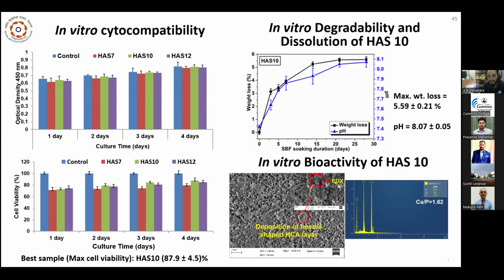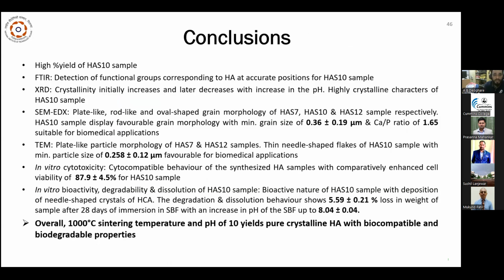Here it shows that a needle-shaped structure is observed with a calcium phosphate ratio of 1.62. From the analysis, it can be observed that at a sintering temperature of 1000 degrees Celsius and pH of 10, it yields pure crystalline hydroxyapatite with biocompatible and biodegradable properties, which is considered for further testing.